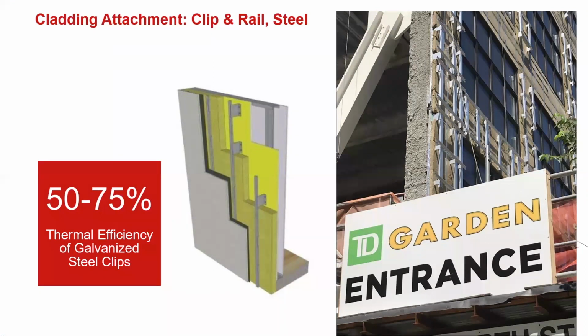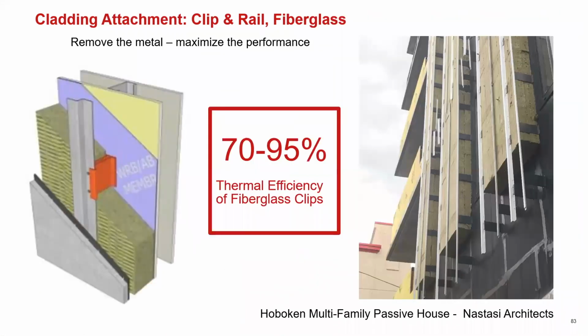So this is a system from a manufacturer called Envelope, where they have clips and rails. If you're just having the clips penetrate the insulation, you're starting to see a much higher performing type of assembly. In this case, up to 75%, although they now have clips that can span slab to slab, and they're getting up into the 90 to 95% effective range. So you definitely want to think about those solutions, as well as fiberglass solutions, right? There are manufacturers out there that manufacture fiberglass clips like this. This was a passive house in Hoboken through Nastasia Architects, where they used 8 inches of semi-rigid stone wool in between the thermally broken clips. So pretty high level of R value there.